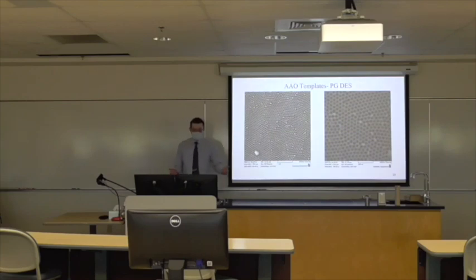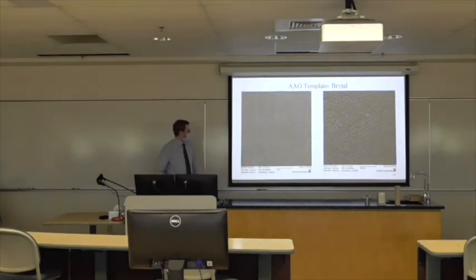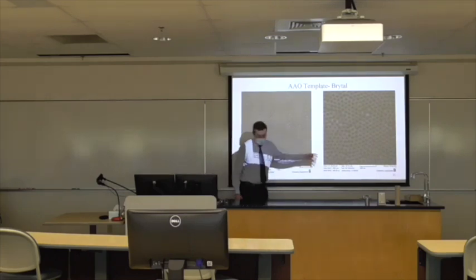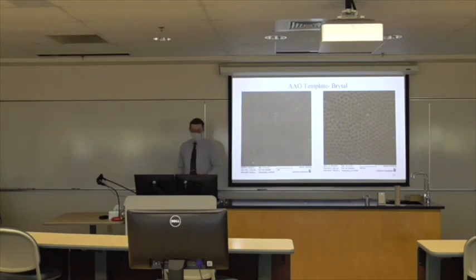To compare that to how it might work with, say, the Brytal electropolishing, we did the same method, but with a Brytal electropolished piece of aluminum, and we get roughly the same results. We have the same pore ordering, we have the same diameter. So both methods work, but the propylene glycol electropolishing does work to make a smooth surface that we can then use for the production of these templates.